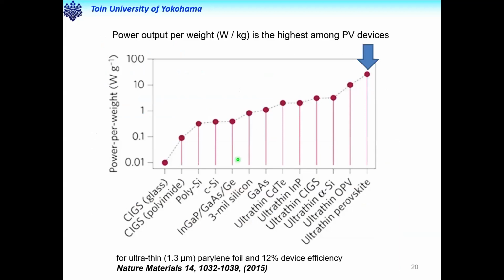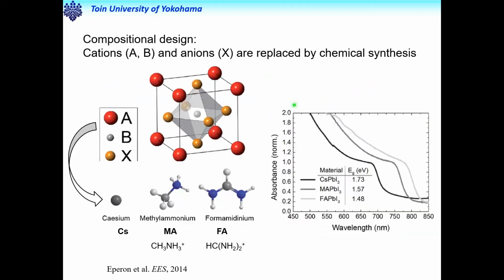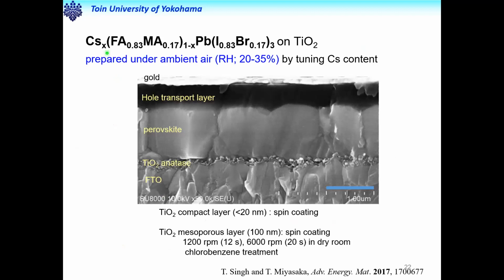Another merit is that the power generated per unit weight is the largest among all PV devices, because the photovoltaic layers can be made very, very thin. But we can also, as chemists, synthesize by changing the cation and anion, replacing the organic cation with inorganic cesium like this. This is a typical so-called multi-cation lead halide perovskite coated on TiO2. You can see very large crystalline grains coated on the TiO2 basement. And I think it's a very beautiful layer structure of perovskite.